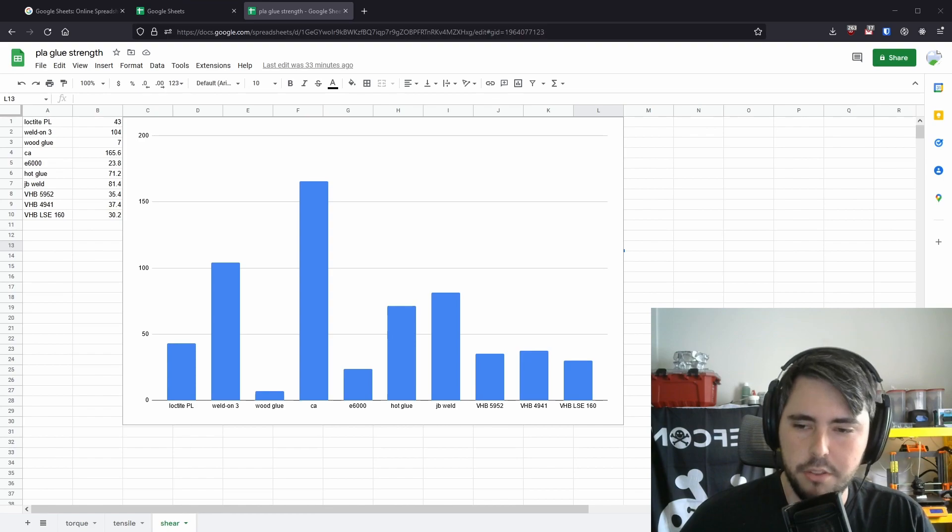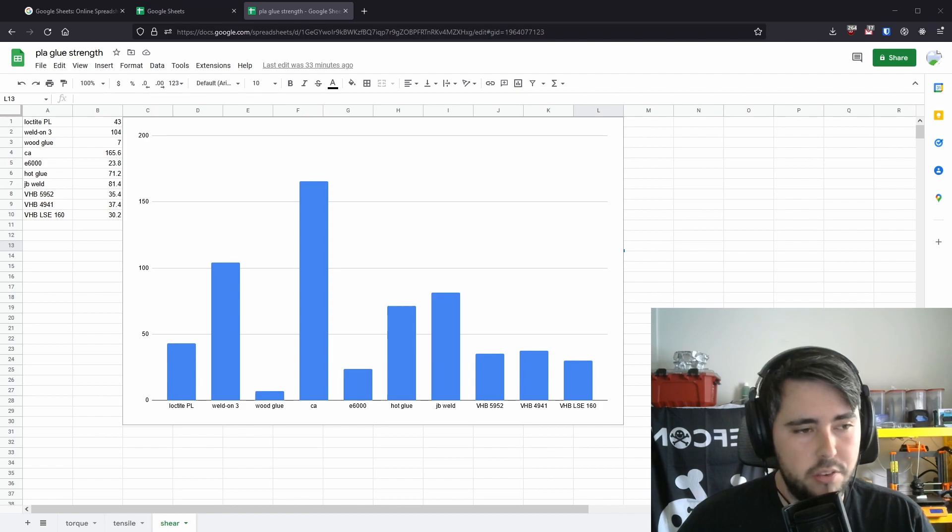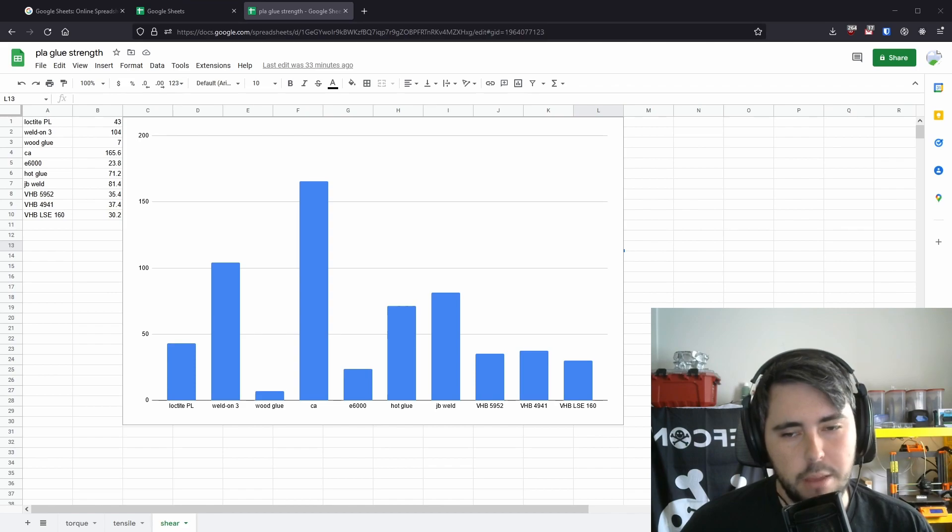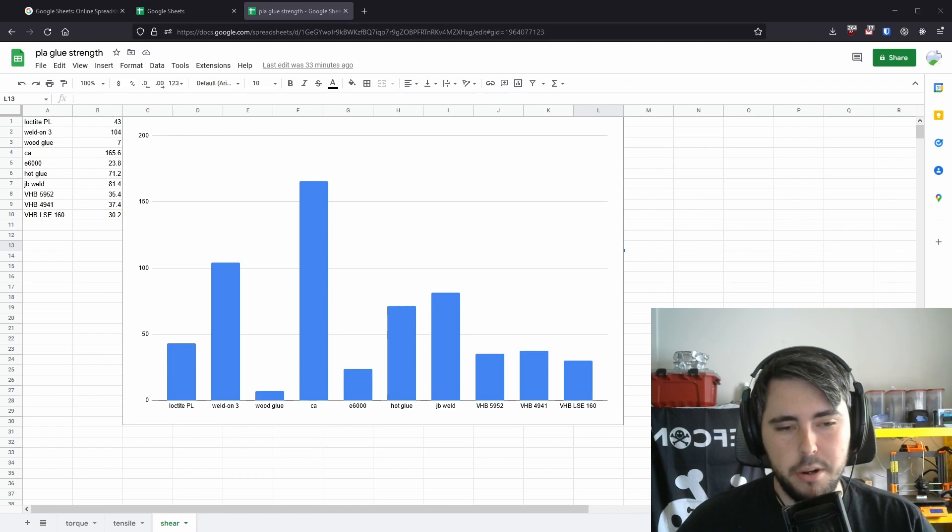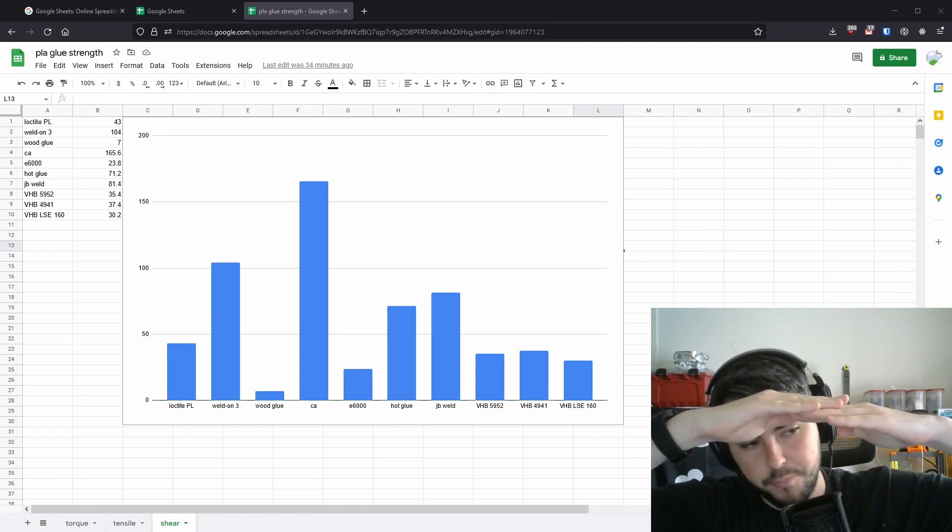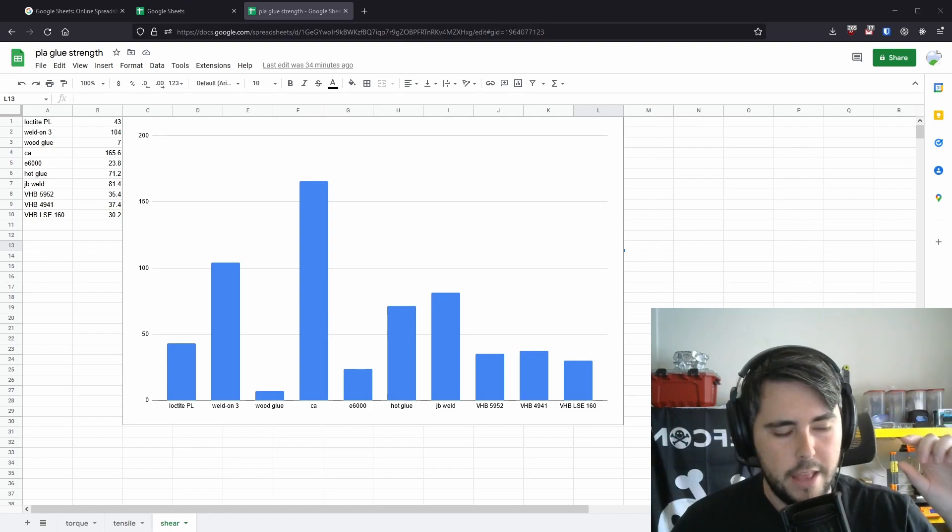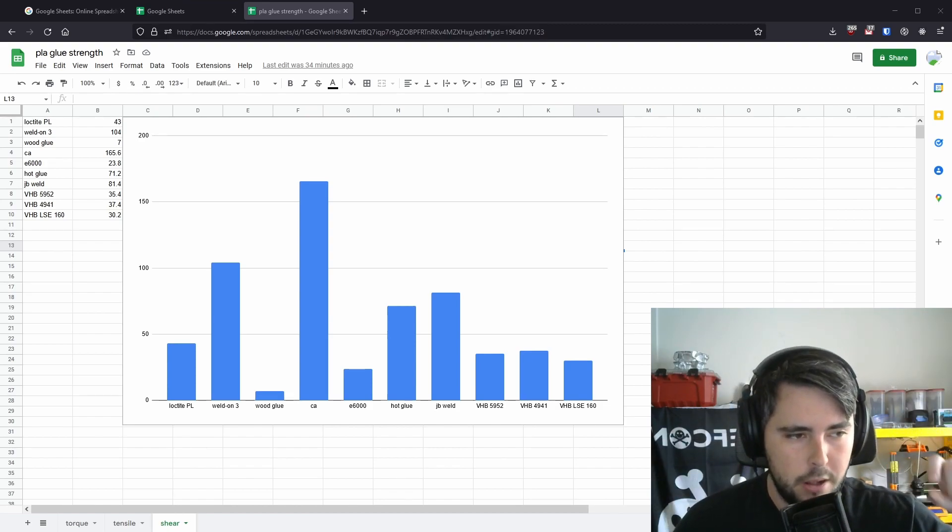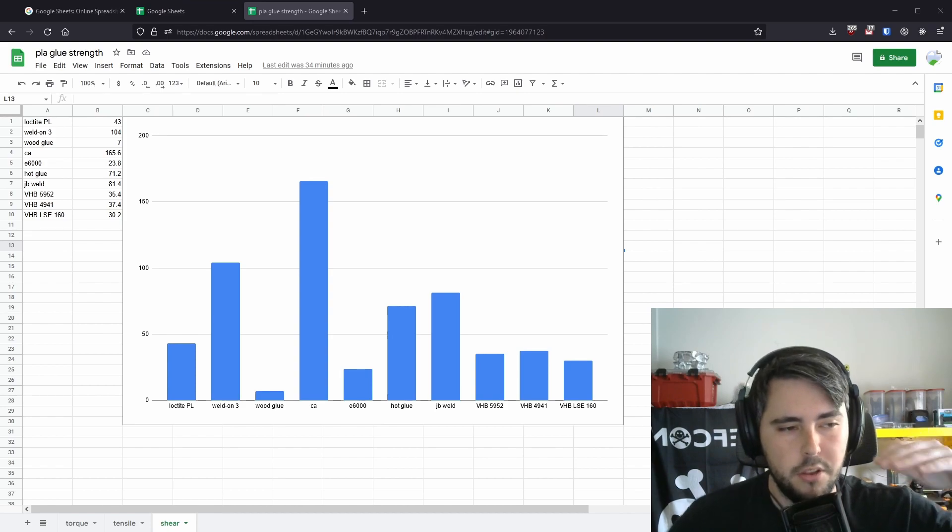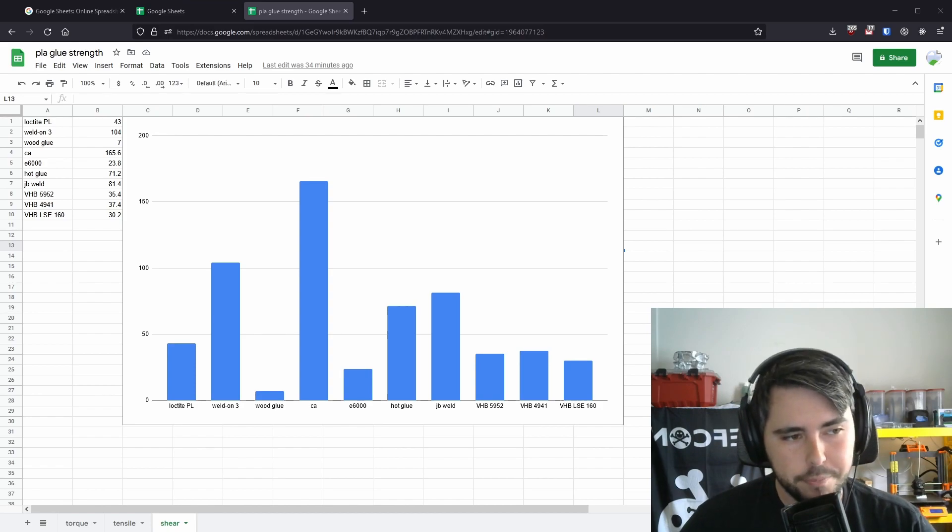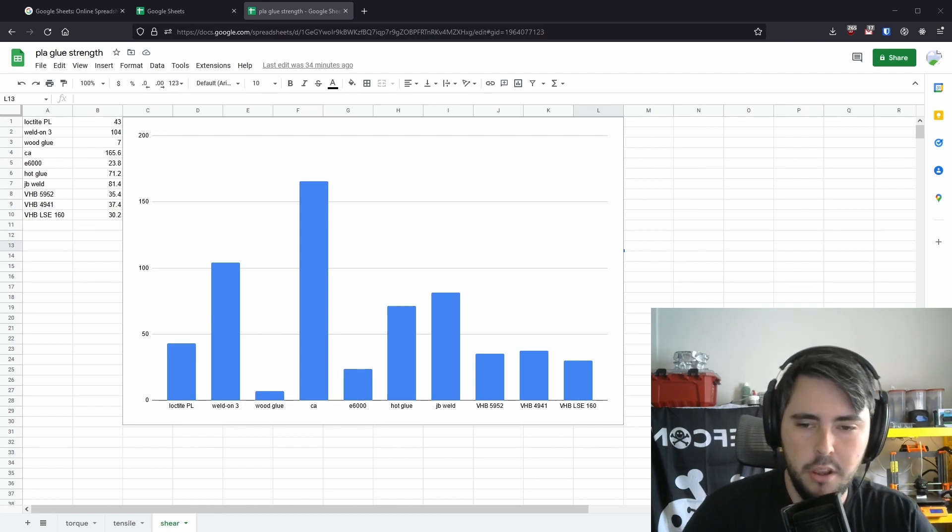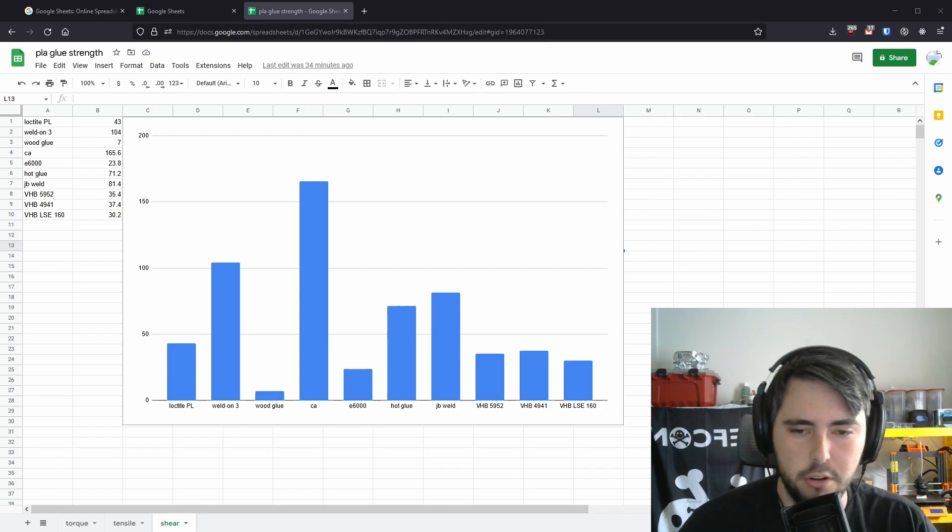For shear strength, again, CA glue did an amazing job. If you need a thin glue, I would say CA glue is the winner. If you need something that can fill a bit more of a gap, JB Weld is the winner here. It's a little bit stronger than hot glue, but there's also a unique property with shear joints. So if you have a shear joint that wants to split apart like this, right, and you can model and control both sides, you can put a through hole through both of the pieces. And then when you go to glob in your JB Weld, it will fill up both of those holes. So it'll basically make a pin of solid epoxy that's through both of the pieces. So when it wants to shear apart, it'll have to shear through that epoxy. That will give you an even stronger joint than anything that we tested here. So JB Weld is great for a shear load.